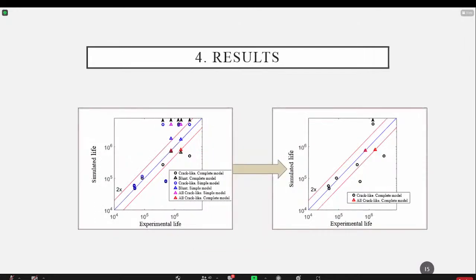If you see in the left diagram, the black triangles model the complete initiation and propagation model, and the red triangles model what happens if you consider that this blunt defect behaves directly as a crack. And we can see that the results are very similar. They are almost the same. So according to our results, we were able to consider all the defects as crack-like.